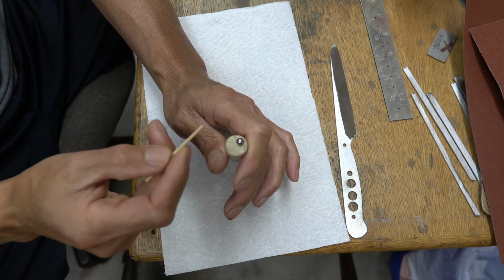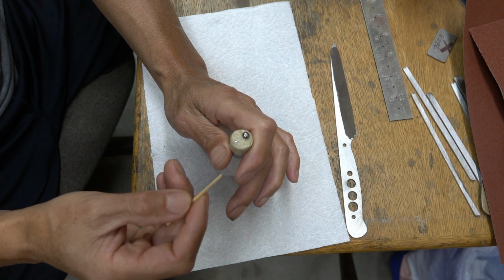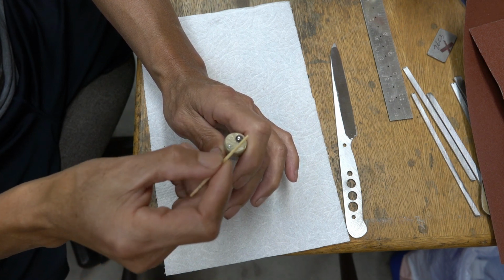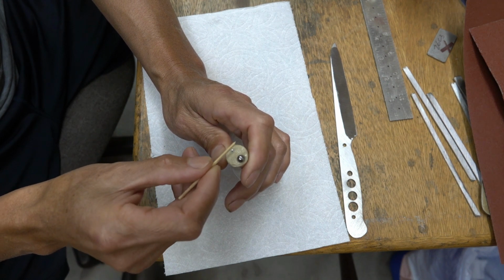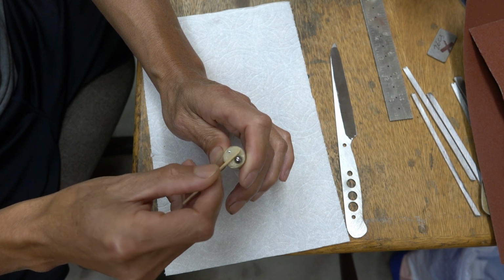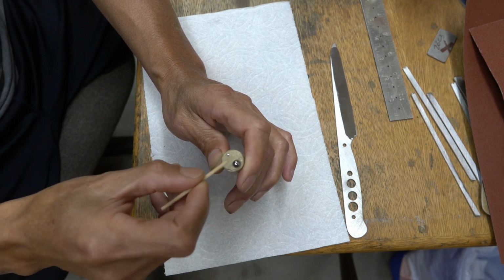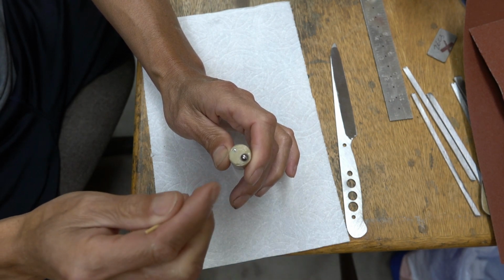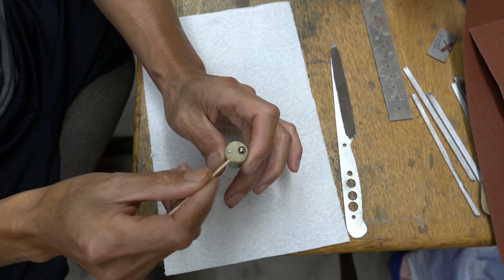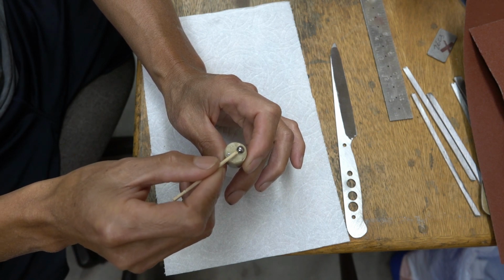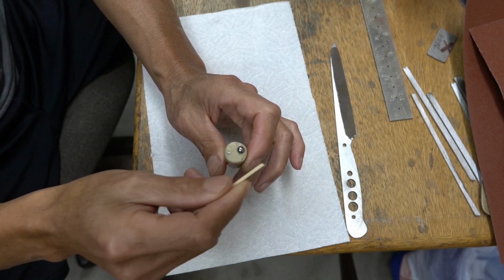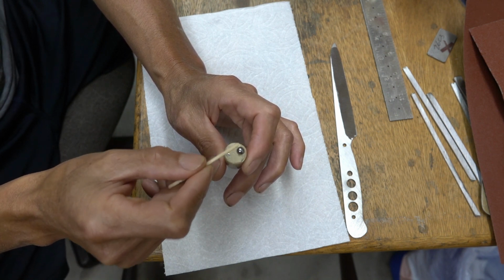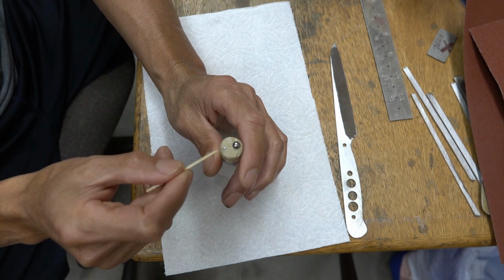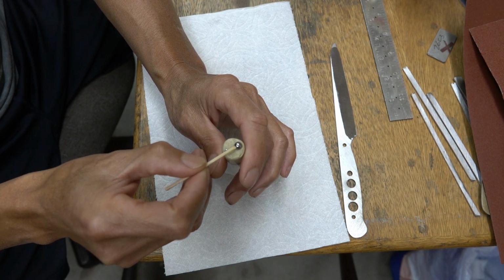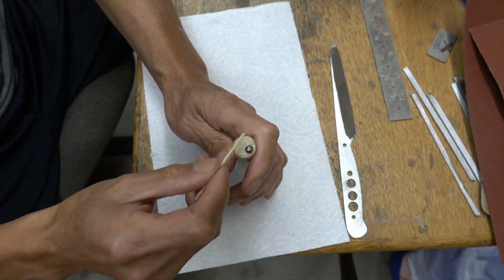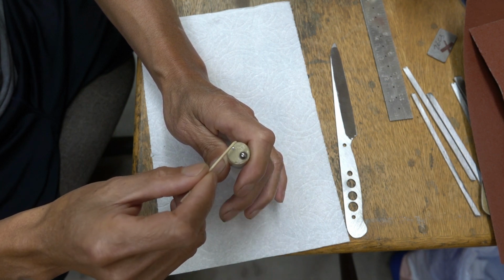Now I use the 8000, and the ceramic abrasive is going to be softer, so what would happen? The abrasive goes through, rubbing, and the loose abrasive is more like rolling and tumbling, and of course some of it will get large and push and try to plow. The fixed abrasive in the stone will have impact, or it would try to abrade or cut the carbide, but it won't do that effectively at all. So basically, you end up with impact.